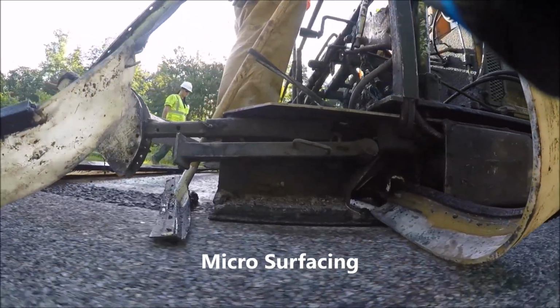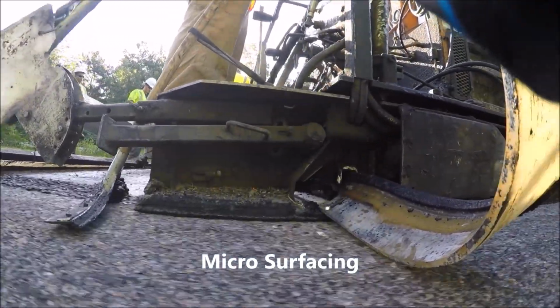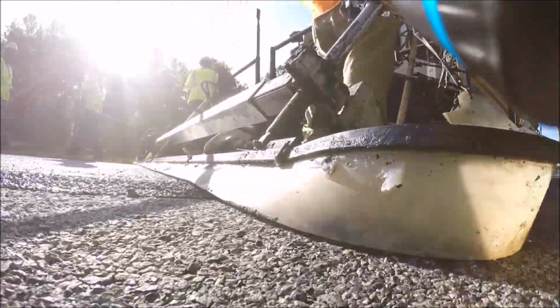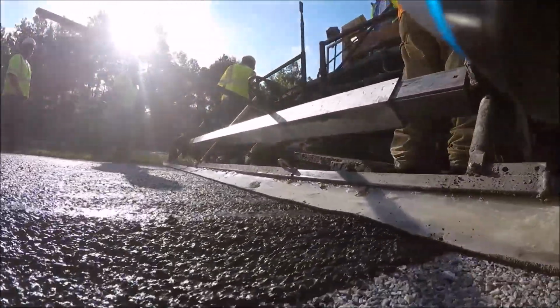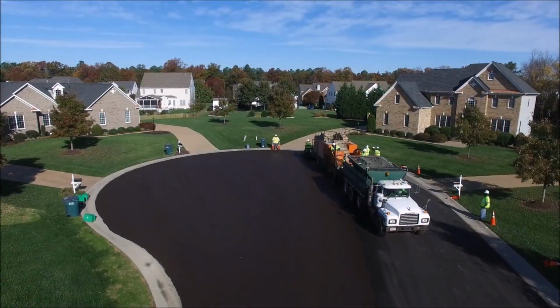And you can see here the first difference between the plant mix operation and the slurry surfacing operations is the thickness. We're starting with roads that are in pretty good shape, and we're just going to apply something about 3/16 or 1/4 of an inch thick to an existing pavement that's in pretty good shape.